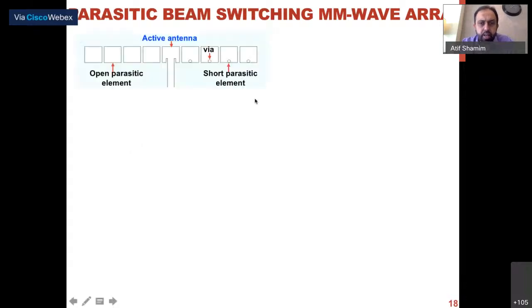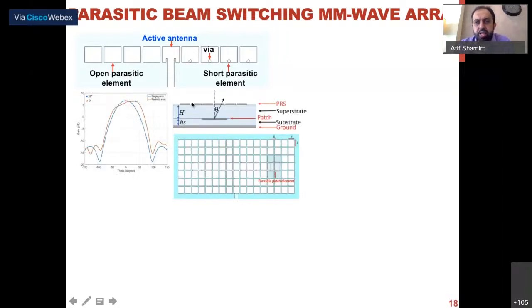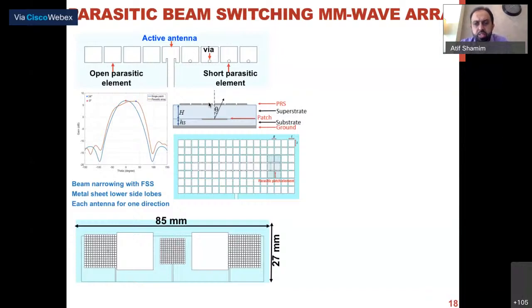So in order to make the beam narrow, we used a partially reflective surface, which is a repetitive structure, a kind of FSS. If you look at the stack up, there's a ground plane, there's a substrate, then there's your feed antenna and the passive array. And on top of that is a partially reflective surface, which can make your beam narrow. We've made three versions of it, and these are the printed versions. You could see that they are again conformal and flexible, and they can switch the beam within plus minus 32 degrees with a maximum gain of 13 dBi at 77 gigahertz. This paper just came out. I forgot to put the reference for it, but if somebody's interested in this, you could look it up. So in a parasitic, flexible way, you are able to switch the beams.